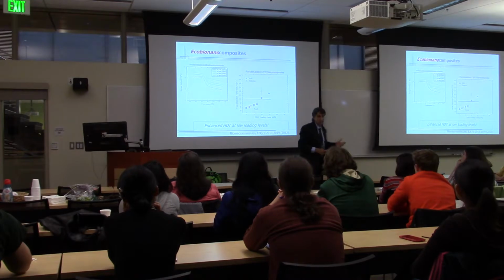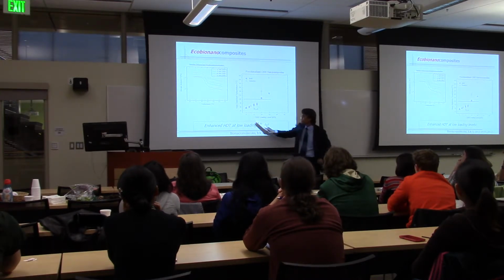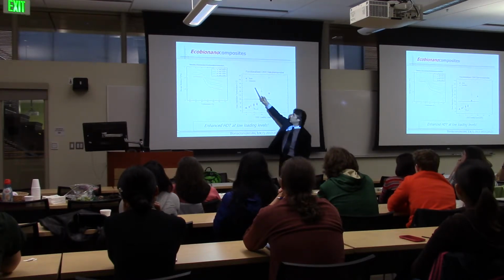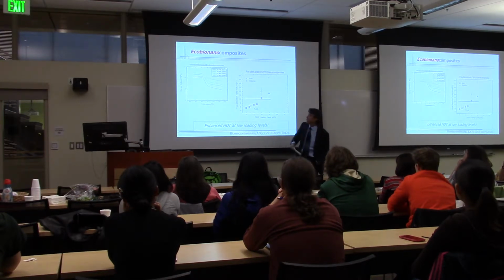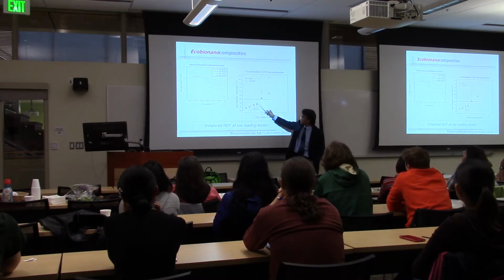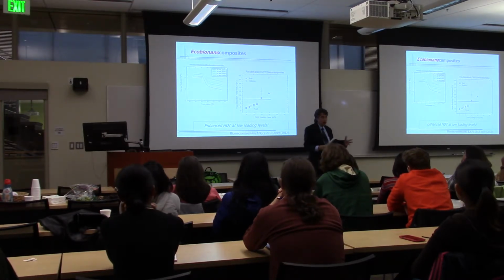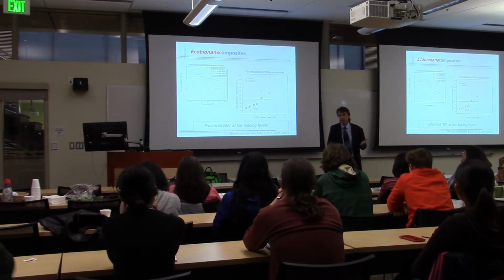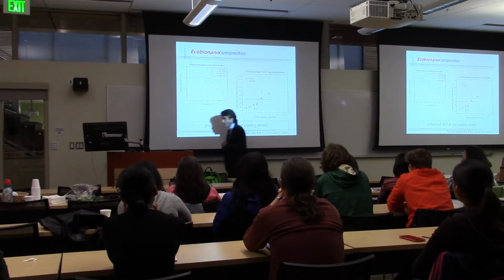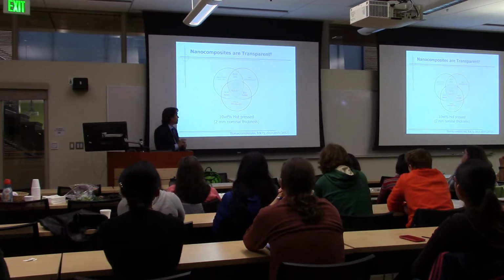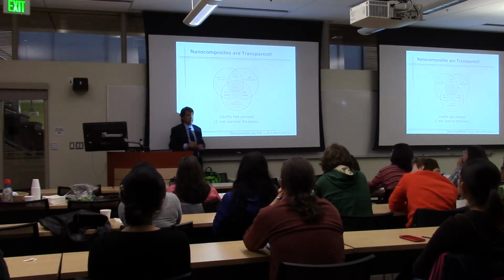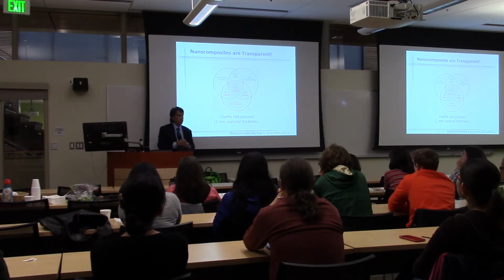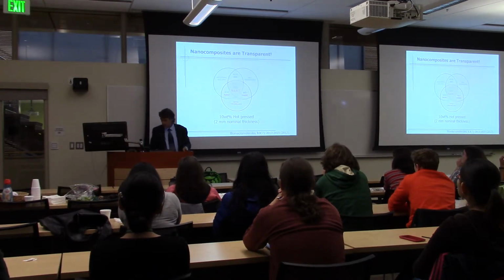And of course, that translates itself into that heat distortion temperature that we talked about before. Now if I look at my heat distortion temperature versus loading, this is increasing quite rapidly. It depends if you do this in bulk or solution. I think when we do the solution polymerization, we just get slightly better dispersion. But you can see at 10% loading, we're able to get above 100 degrees centigrade. And of course, that's the target for many different applications because you can hold boiling water at that point. So you can do sterilization and all kinds of things. And so here is a picture of the nanocomposite in the middle. You can see that we've done a good enough job through this nanotechnology approach of controlling the chemistry to get the nanowhiskers so finely dispersed that the material does remain transparent.